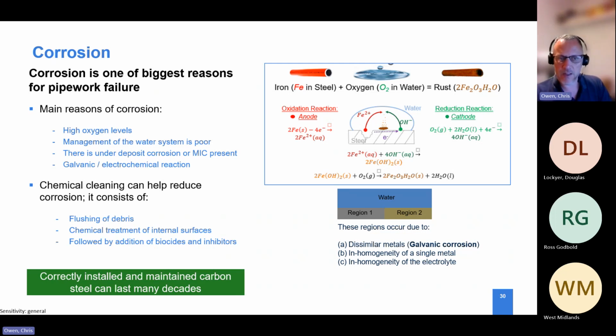Now, I don't want to say carbon steel is always at risk of corrosion, because correctly installed and maintained carbon steel tube can last many, many decades. And most people tend to allow for some sort of corrosion allowance when they're doing their design. What we're saying is we can work more closely with you to look at the application, at how the pipe work is being installed, and at the grades of steel. Higher grades of steel will allow you to go to thinner walls and have an initial resistance to the onset of corrosion. So we try to be more responsible with the amount of steel we use, looking at weight savings, which then result in embodied carbon savings as well.